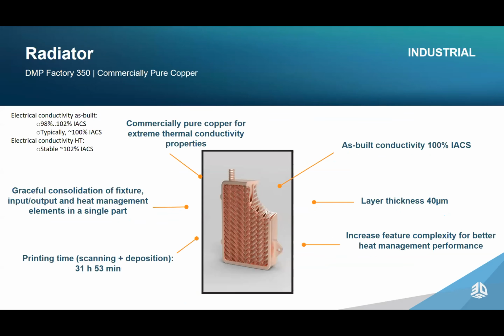Here's a heat sink we actually show quite a bit. We printed it in copper, and you can see fine features, and again, stable conductivity after heat treat at 102% on this one. And typically we're again about 100% IACS as built.